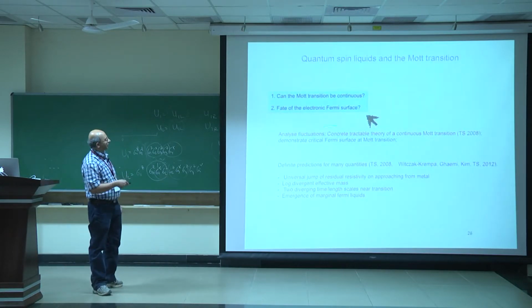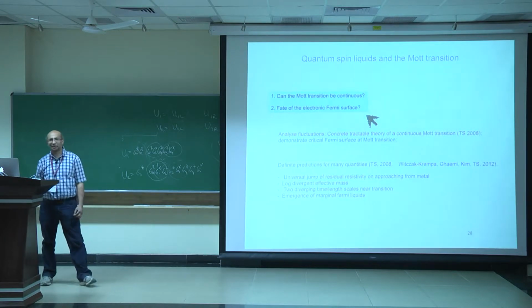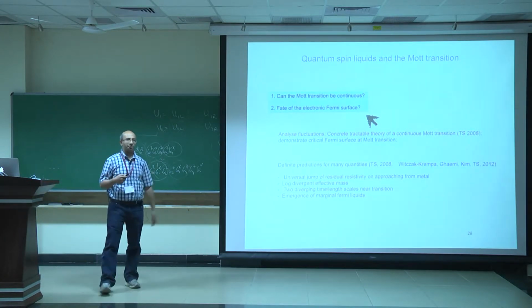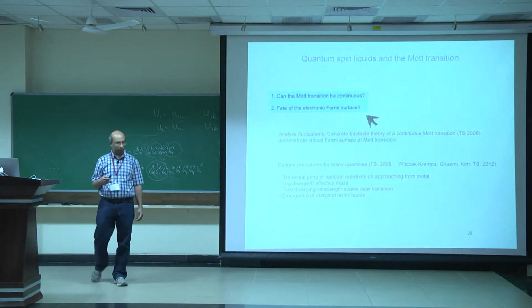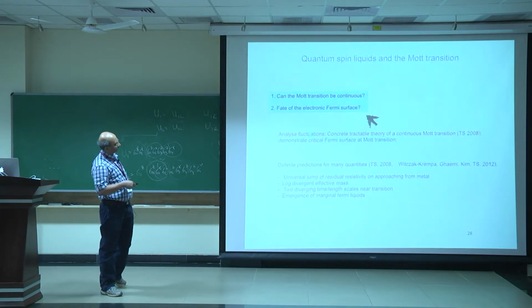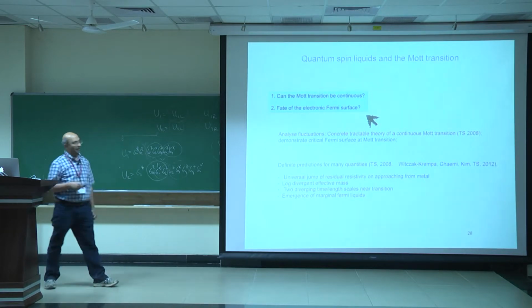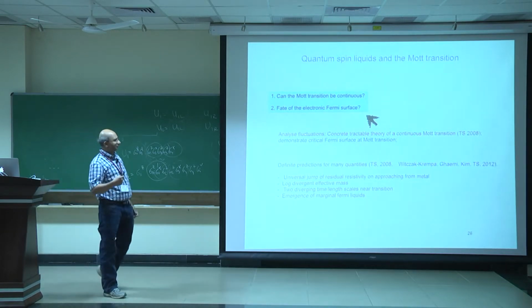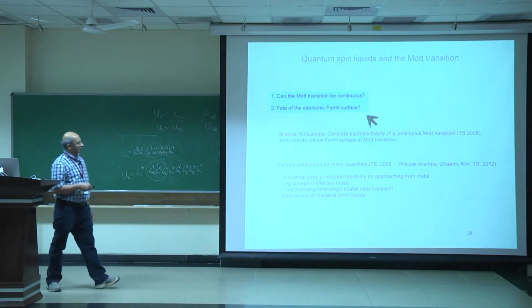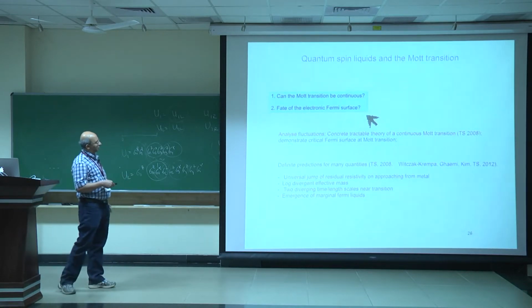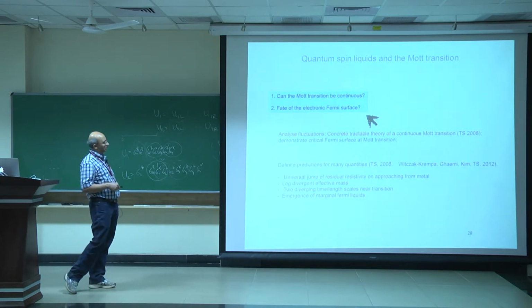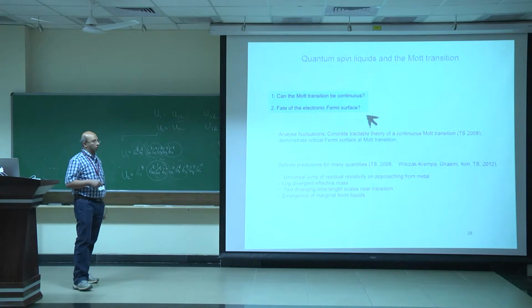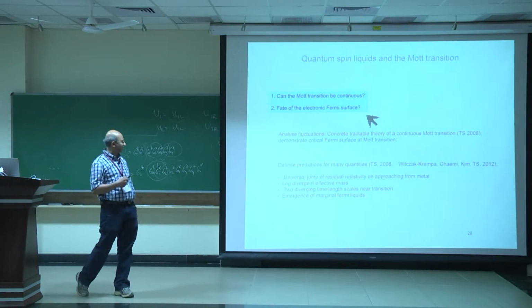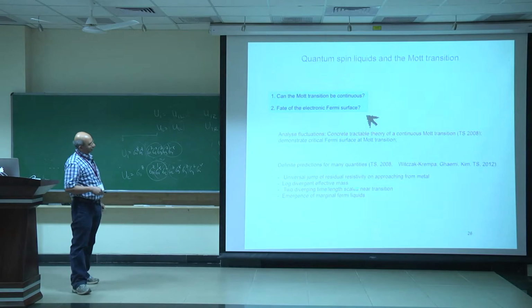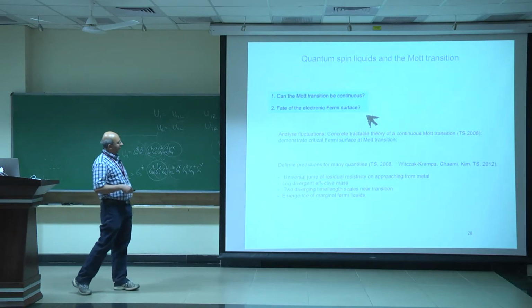So can the Mott transition be continuous, and what's the fate of the electronic Fermi surface? Now it turns out that based on the slave particle framework and analyzing fluctuations, several years back I was able to develop a concrete and tractable theory for a continuous Mott transition from a Fermi liquid to a quantum spin liquid. And this theory was tractable enough that one could demonstrate the emergence of this critical Fermi surface at the Mott transition. And it leads to a number of definite predictions for many different quantities. I won't describe all of them. I'll describe some of them in the next few slides. But let me just list some of the predictions.